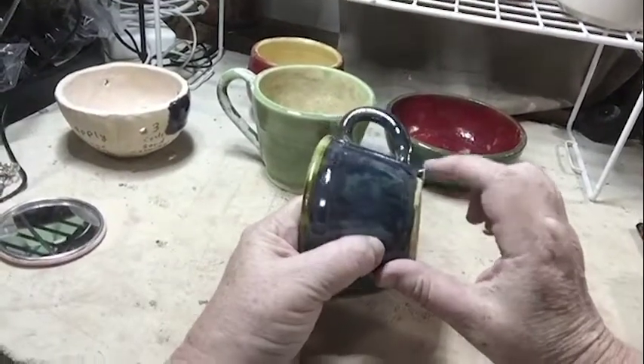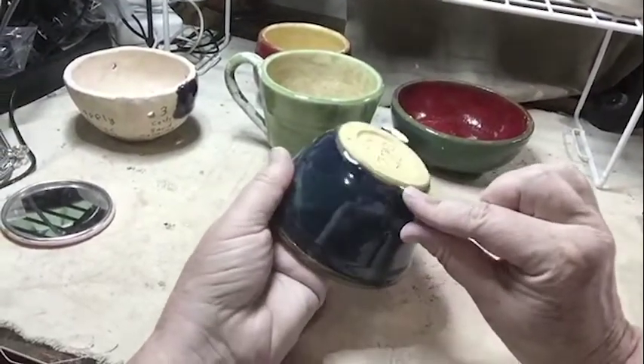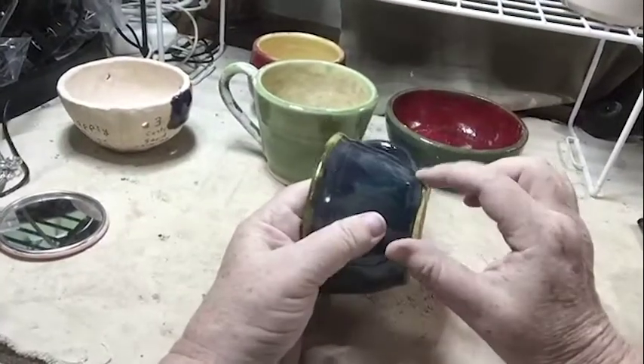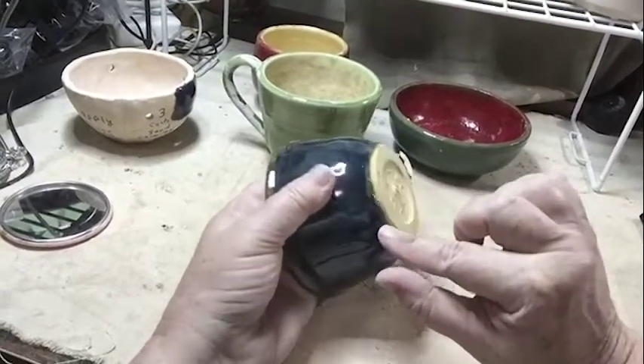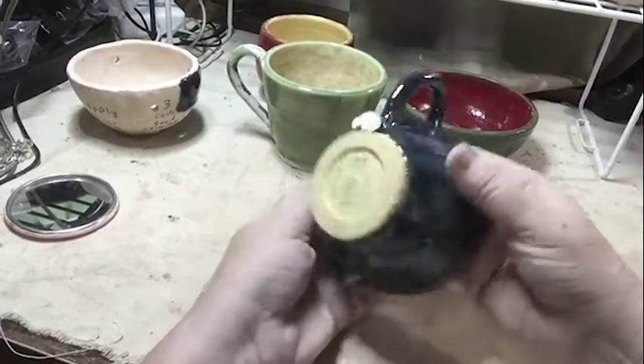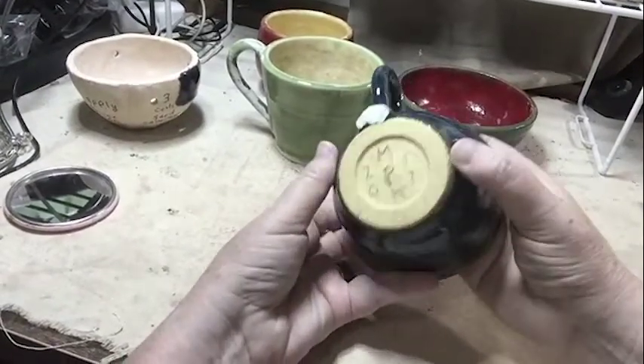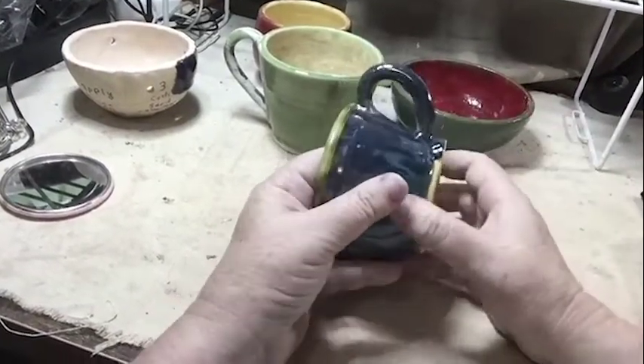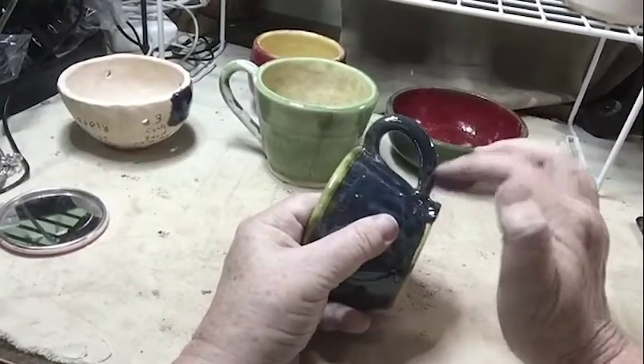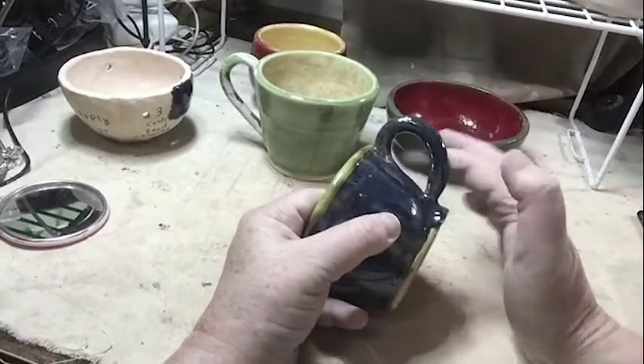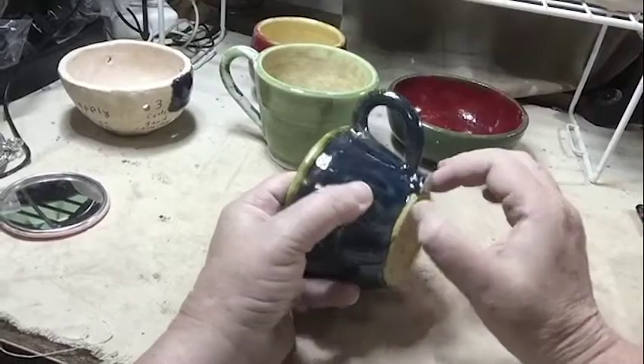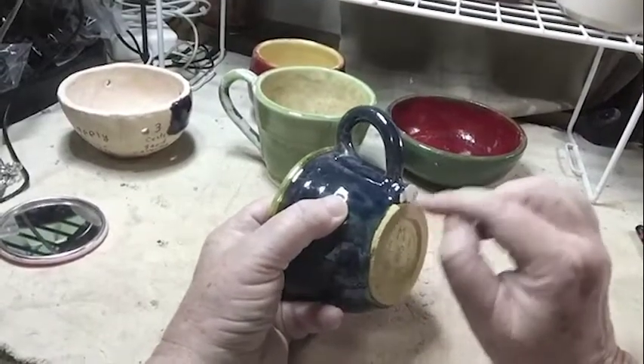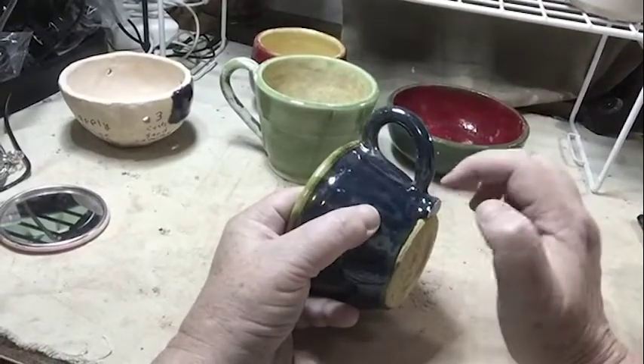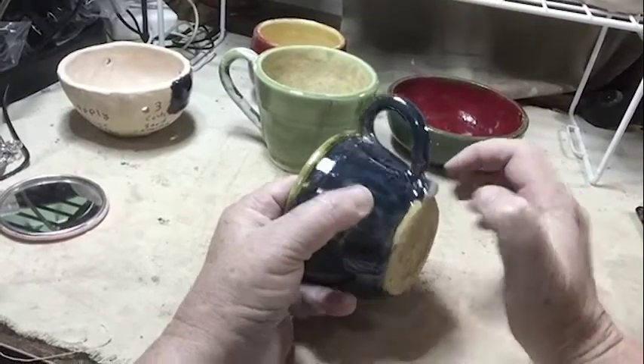Luckily, I kept enough room down at the bottom of the piece here that where the glaze ran down, it just ran down, and there was enough of the bottom of the piece there to allow that glaze to run down and be okay. But I got too much glaze on the handle there, and it all sort of ran together with the glaze that's on the side there, and there was not enough clay under here to compensate for all the motion of that glaze there.